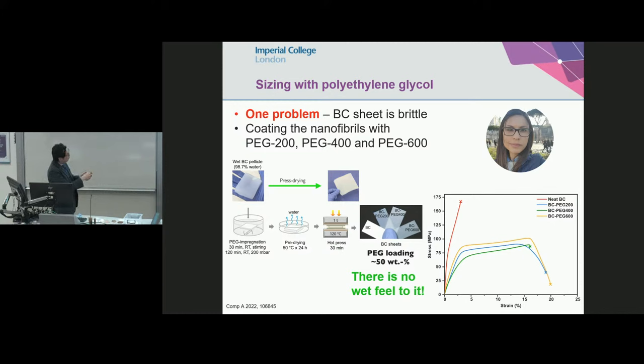So without that polyethylene glycol coating, it goes up, brilliant, it breaks. With polyethylene glycol, it goes up, it keeps going through plastic deformation, rather ductile, and it breaks afterwards. So you're actually getting that significant improvement in what we call strain at failure. How long, how much can you stretch before it actually fractures?